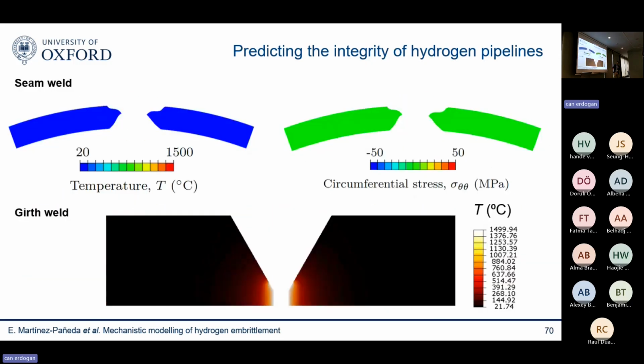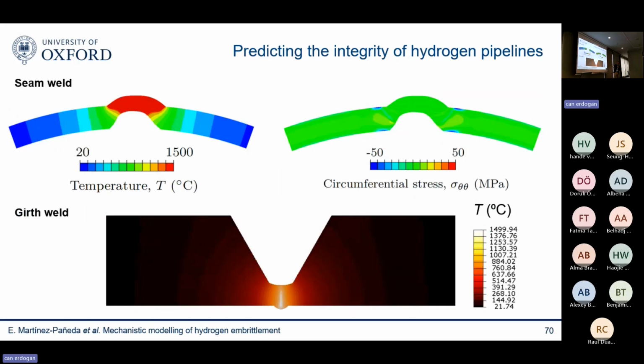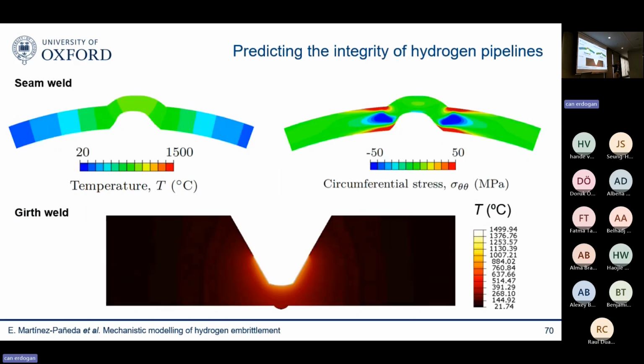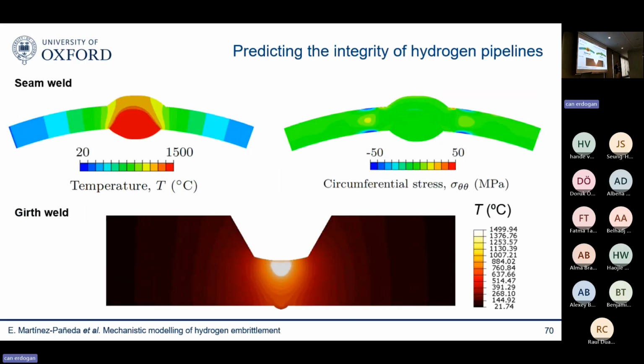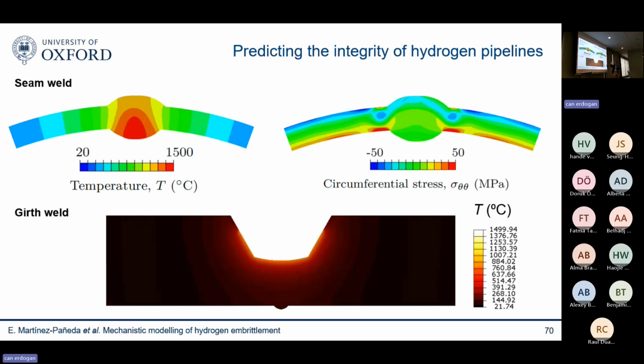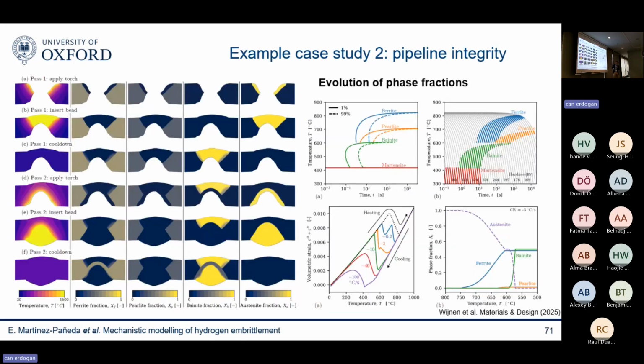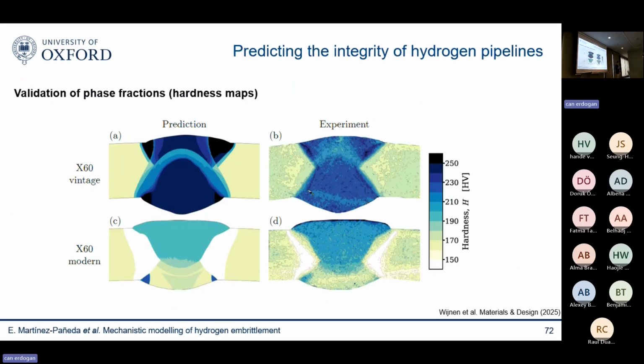So here what you see is a girth weld, multiple passes, and this is a seam weld where you have a couple of passes, and you're able to predict the phase volume fraction and, of course, residual stresses. And you see here the different phase volumes, austenite, bainite, and so on. So depending on your cooling rate, depending on your welding process, of course, you get a distribution of different phase fractions. And if you have different phase fractions, then you're able to predict different hardness levels. And you can validate them with experiments.